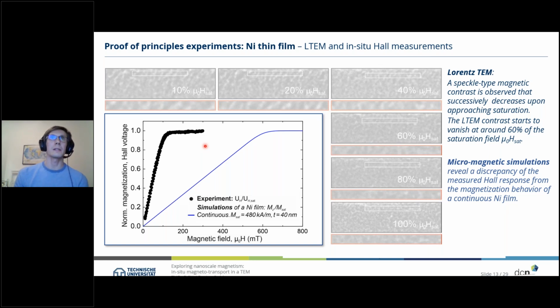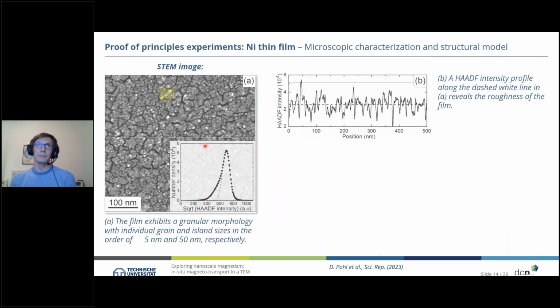But we thought, let's use the power which we have, since we have the sample in the transmission electron microscope, and let's study in more detail how our sample really looks. So we did high resolution STEM imaging, so scanning transmission electron microscopy, here in a HAADF setup, where you can then see the nickel film popping up as brighter contrast as compared to the background.